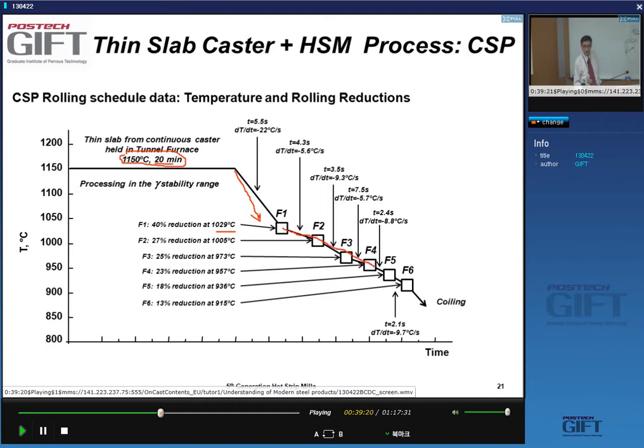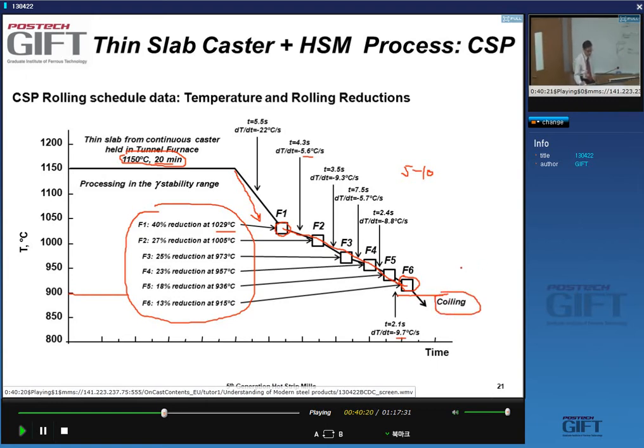And in this case, we have 6 stands, yes? The temperature decrease is 5 to 10 degrees per second, and you can see the reductions here. They go from high reductions at the beginning to much lower reductions towards the end, very similar to the type of reductions we see in the finishing of a hot strip mill. Okay, and again, the end temperature here is high enough so that you process the materials generally in the fully austenitic range, and you do the transformation in the laminar cooling.